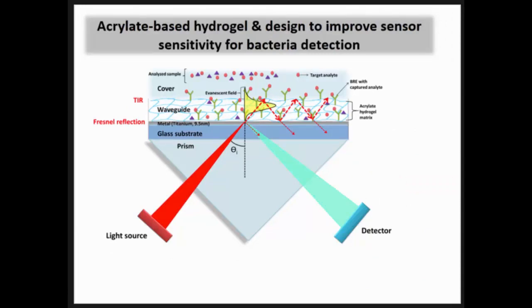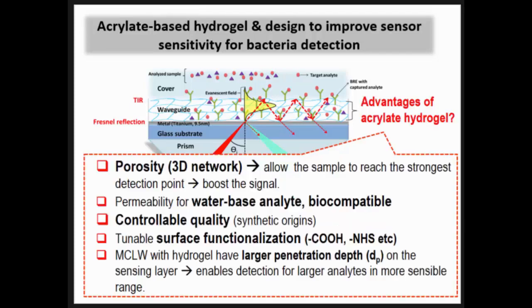For my project, I use acrylate-based hydrogels to improve the sensor sensitivity, because my project is about detecting bacteria. Therefore, we require acrylate hydrogel matrix as a waveguide sensing layer. The first reason is the porosity: the nature of the acrylate-based hydrogel is to have a 3D network, which allows the samples to diffuse in and reach the strongest position where the detection happens. Therefore, it can enhance or boost the signal.